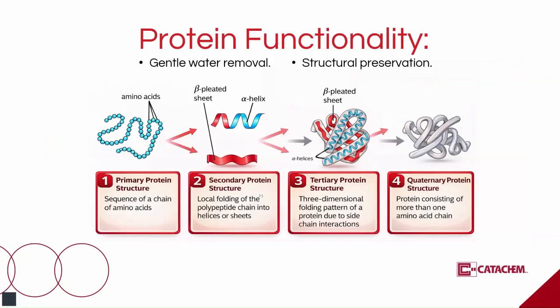Addressing shelf life extension directly, proteins are structurally complicated, as this slide illustrates. Add water and complications increase. Most degradation mechanisms in biologics and diagnostic reagents depend on water. Hydrolysis requires water. Many mobility-driven reactions accelerate with higher water content. Microbial growth requires water. Ice crystal melting and refreezing cycles in liquids can damage proteins during shipping. By removing water, lyophilization reduces the rate of these pathways dramatically. It does not eliminate all degradation, oxidation and other pathways can still occur, but it shifts the system into a much more stable state. In practical terms, a properly designed lyophilized product can maintain activity and calibration integrity longer, tolerate broader shipping conditions, reduce reliance on cold chain, and reduce waste and lot failure risk for the end user.